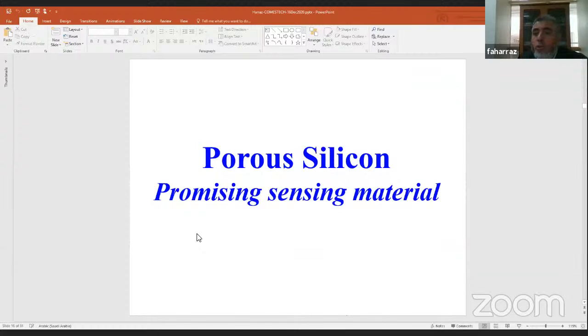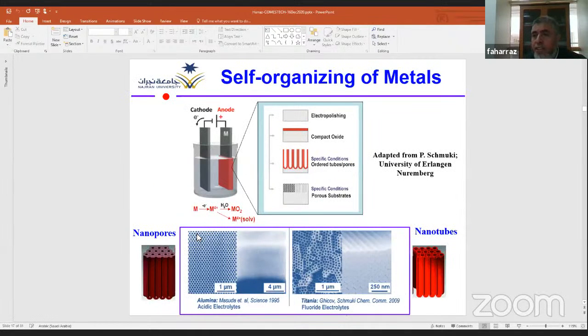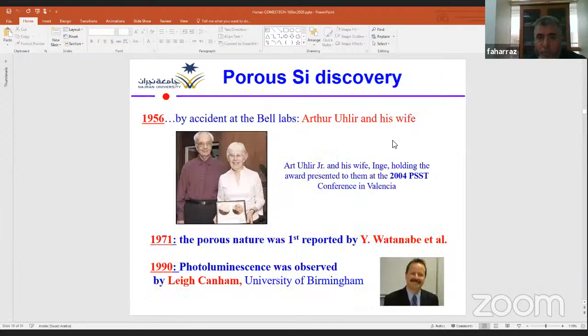Okay, let us now go to the first part of my talk about the sensing application using porous silicon. Porous silicon actually is a promising sensing material, and like alumina and titania, porous silicon can be fabricated via self-organizing using electrochemistry, by the electrochemical anodization of a silicon wafer in hydrofluoric acid containing some surfactant.